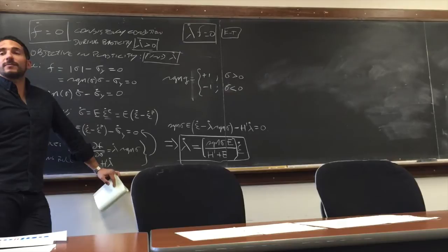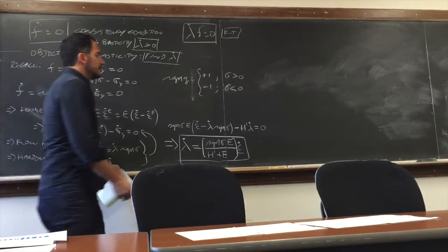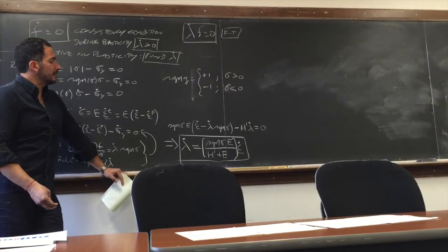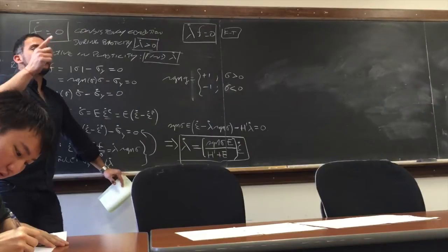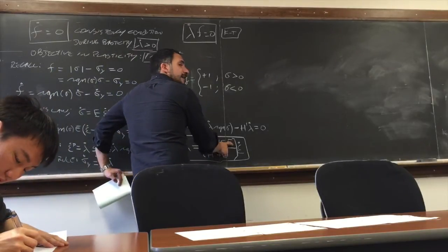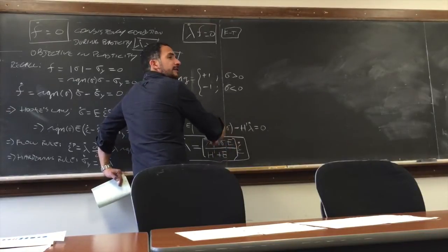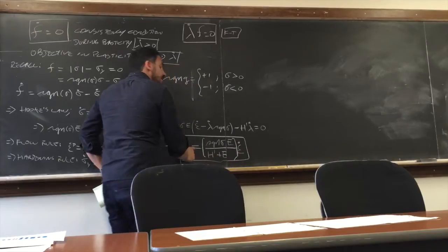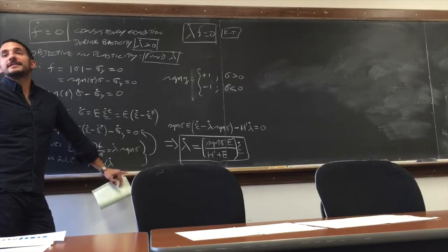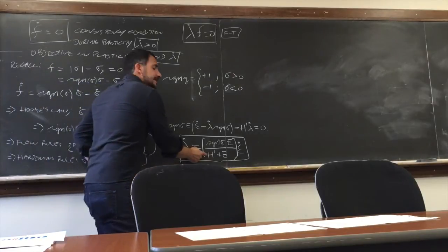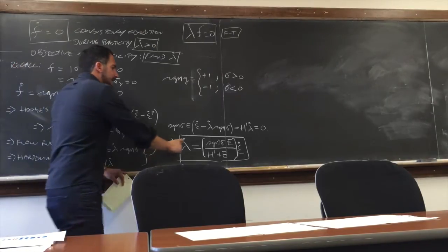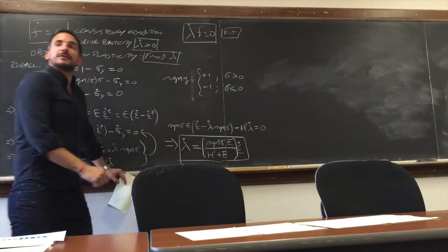Right? H prime equals 0 is pure plasticity. So your total strain increment should all go to your plastic strain increment. Now, H prime going to infinity is approaching elasticity again, right? You go back to an elastic type process. So this remains bounded, the bottom goes to infinity, so this whole thing goes to 0, even though this is non-zero. So lambda dot goes to 0. That means you are getting essentially 0 increments of plasticity as this guy approaches infinity. Okay? So you're always in between 0, gaining nothing plastically, and approaching epsilon dot.